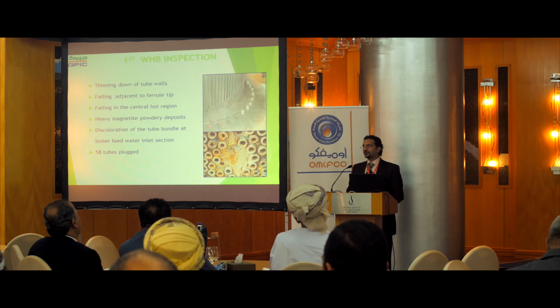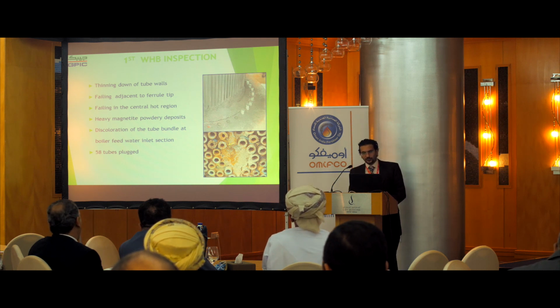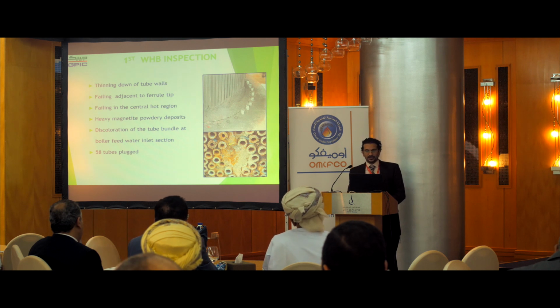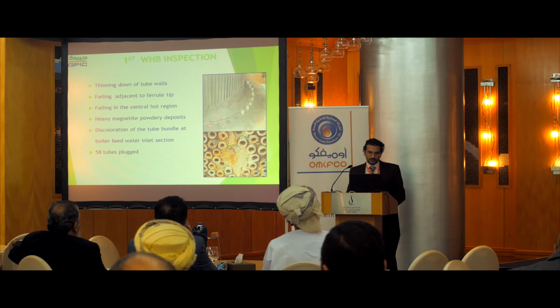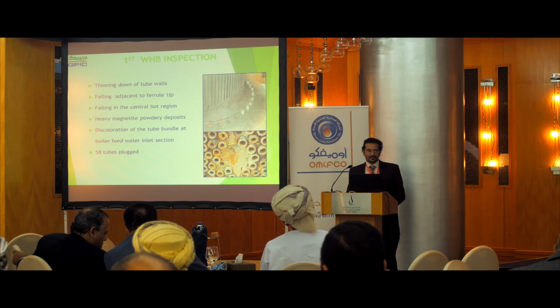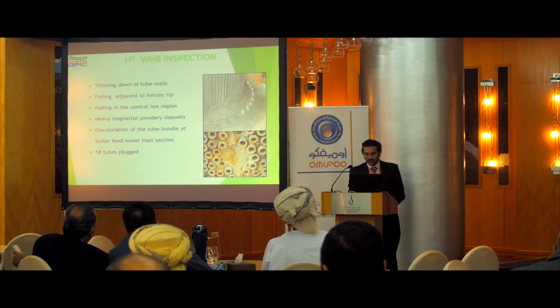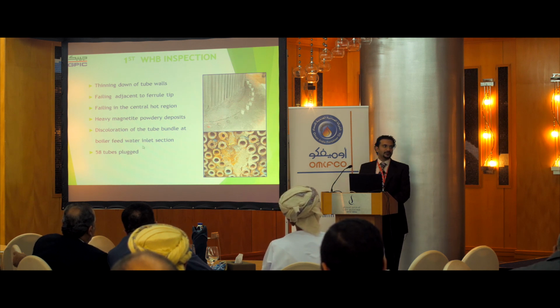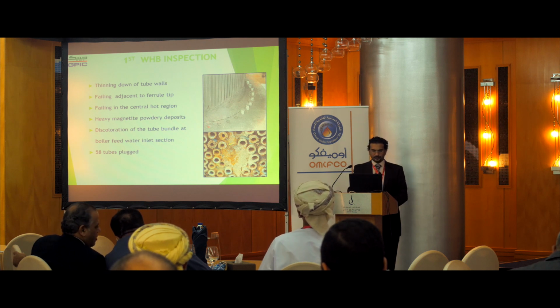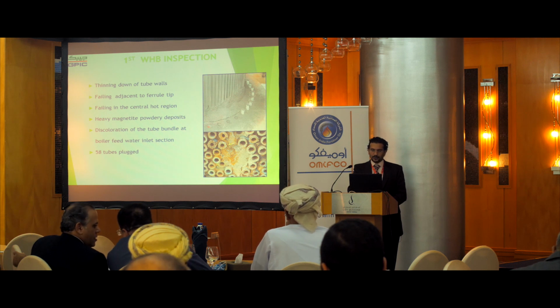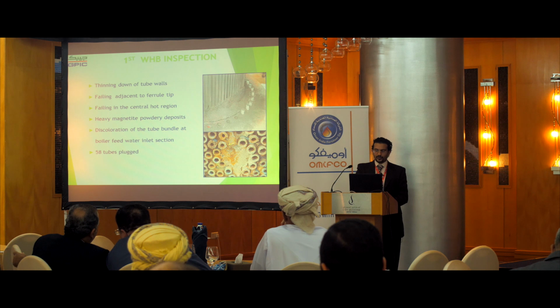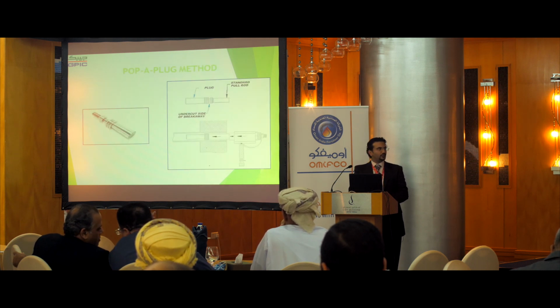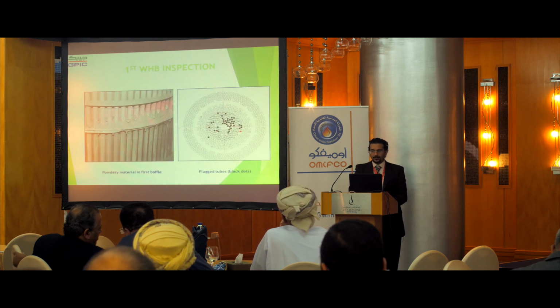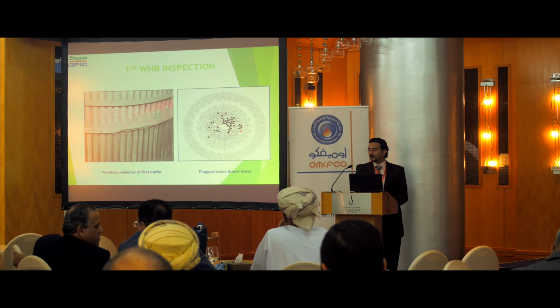After opening and inspecting our first waste heat boiler, we saw thinning of the walls, failing adjacent to the ferrule tip at the tubes. This mostly was happening in the central hot region, with heavy magnetite powdery deposits, as we can see here in the photos, and discoloration of the tube bundle at the boiler feed water inlet section. After studies and going back to our providers, we decided to plug 58 tubes using the pop-a-plug method. These are still photos of the first waste heat boiler. You can see the powdery materials in the first baffle.